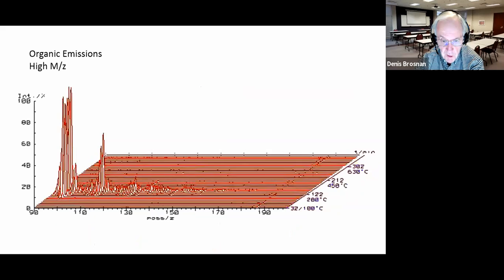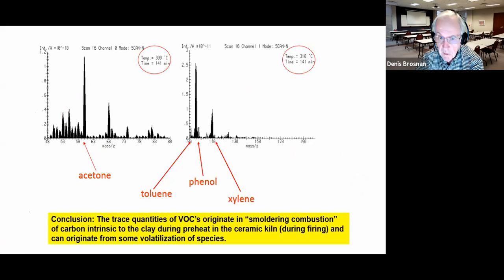If we go up to much higher molecular weights in this firing or heating, we begin to see things start showing up at very high molecular weight. It's a mass spectroscopy instrument, so this curve is generated as a function of mass over charge. But nevertheless, we begin to see other things showing up. And they're identified right here at a couple of different temperatures, a couple of slices of that chart. And some of the things that we see are acetone being generated, toluene, phenol, and xylene.